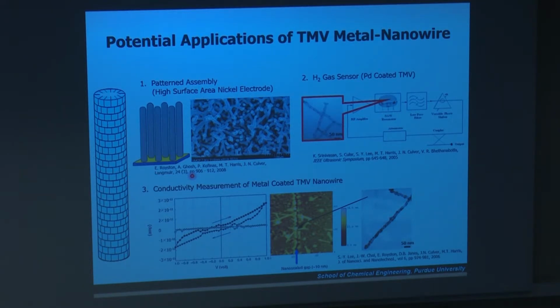We also use it for detecting hydrogen, the second item here. I gave a presentation at the ASHE meeting, and this professor here asked me if I could send him some of these palladium-coated TMV, and he put it on an acoustic wave device and was able to detect hydrogen, because the palladium would absorb the hydrogen, produce palladium hydride, and in the absence of hydrogen, it would release hydrogen from the palladium hydride, and so you have a swelling and contraction of the palladium, which was very good